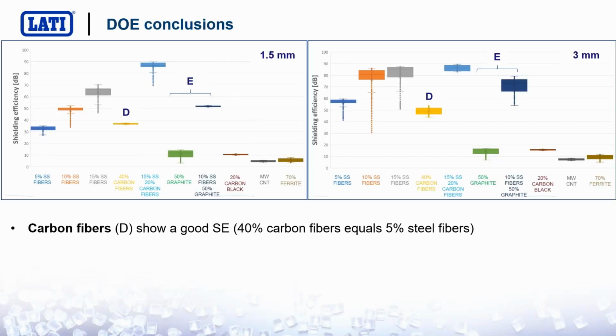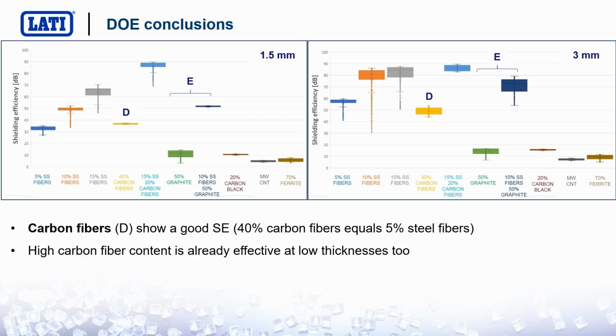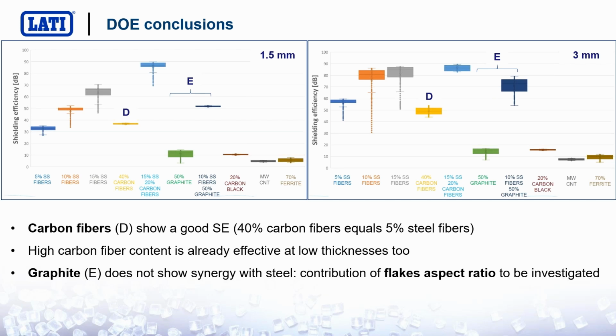Last slide of my presentation. Carbon fibers show a very good shielding efficiency acceptable for most applications, up to 40, 50 dBs, which is very nice because it is more or less the numbers of 5% steel. And carbon fiber is already effective at very low thickness. Graphite did not show very efficient behavior or synergy with steel. For sure, we have to improve the dispersion. We have to change the aspect ratio of the flakes, and we also have to study what happens adding some carbon fibers and steel to graphite.